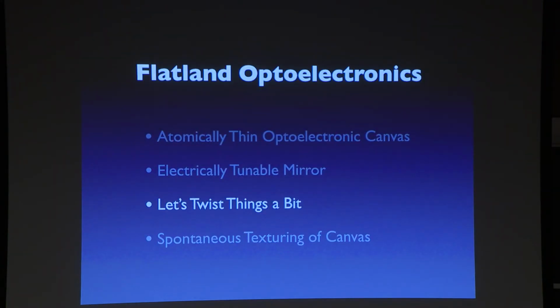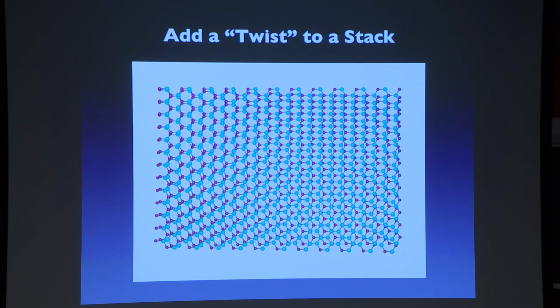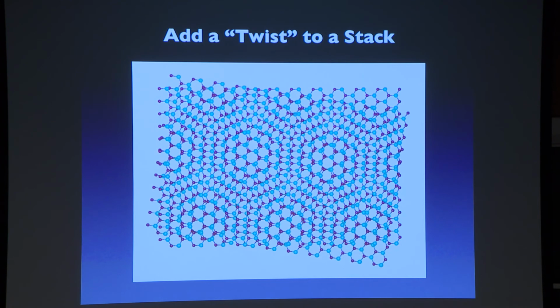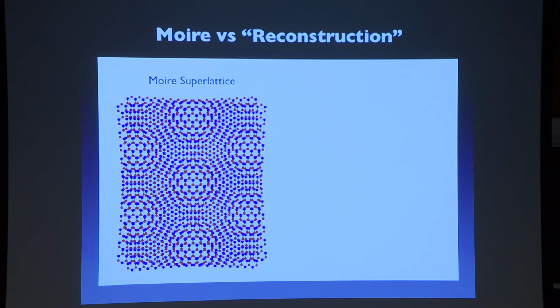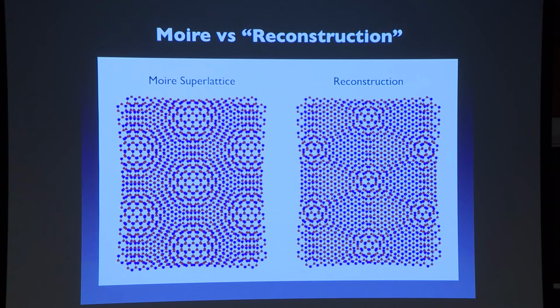So that was one easy example of what twisting can do. But another thing that we wanted to do is to see whether we can investigate in a much more detailed fashion. So let's end this particular talk by talking about this spontaneous texturing. I already showed you this slide and showed you that the twisting can lead to an interesting pattern known as a Moiré pattern. One thing that I did not tell you is that these are fiction, meaning that when you actually introduce these little angles, then atoms actually do not sit like this, but rather they decide to find a more comfortable position and then reconstruct themselves so that we can start to generate these different domains.